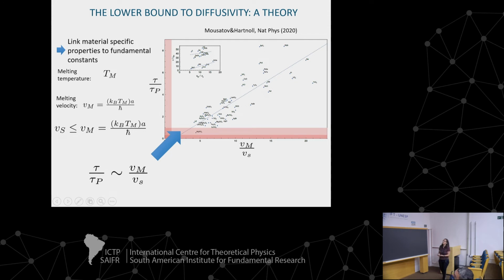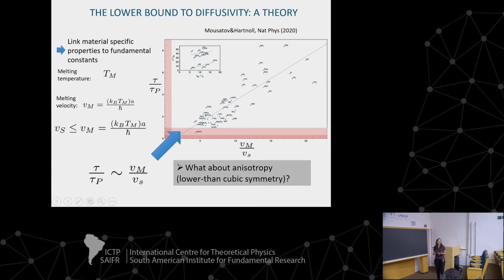This work is very interesting, but it also left open some questions. Mainly, the materials that have been plotted there are either cubic, so showing the highest symmetry or isotropy somehow, or they are polycrystals. Therefore, it was missing what the role of anisotropy is. So could we extend that to a material that finally shows anisotropy? Clearly, anisotropy in thermal conductivity and thermal diffusivity is rarer than in other electronic properties, where it is more clearly displayed.